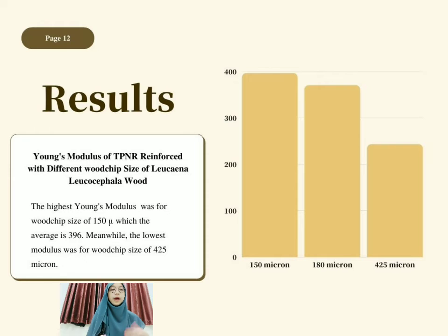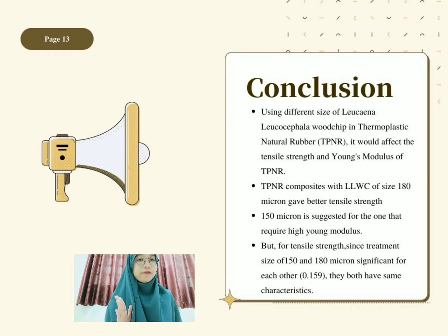In a nutshell, using a different size of Leucaena leucocephala woodchip in thermoplastic natural rubber surely will affect the tensile strength and also Young's modulus of TPNR. And the TPNR composites with Leucaena woodchip of size 180 micrometer gave better tensile strength. Meanwhile, the size of 150 micrometer is suggested for those that require high Young's modulus.